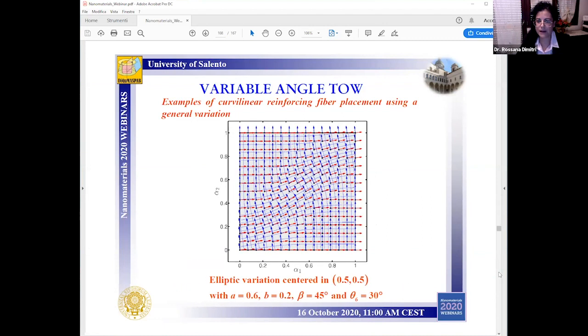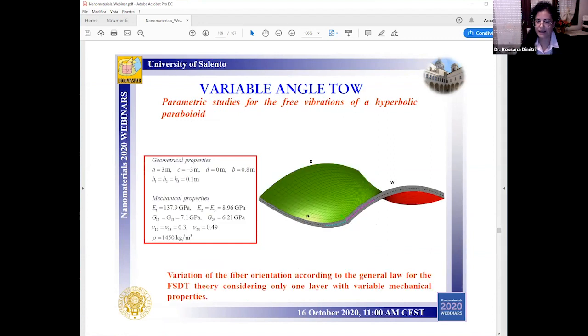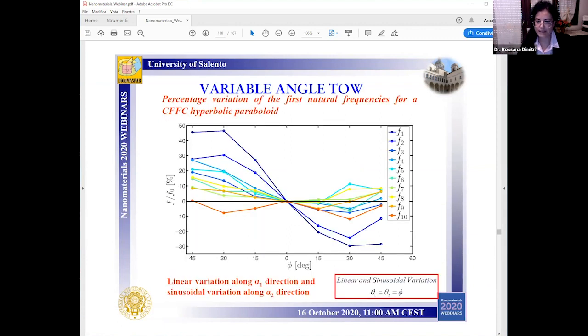And have a look here now, where we represent some examples related to the application. So, I mean, here we have a hyperbolic paraboloid made of 1 layer with variable mechanical properties, where we focus on the variation of the fiber orientation according to the general law for the first order shear deformation theory. And look at the sensitivity of the response, especially for the first frequencies, when we vary the parameter phi between minus and plus 45 degrees, while assuming a linear and sinusoidal variation of the fiber orientation along the alpha 2 direction.